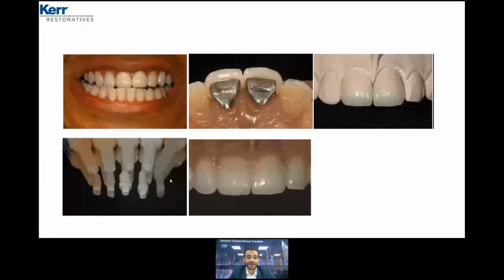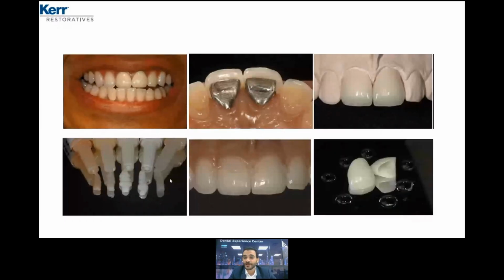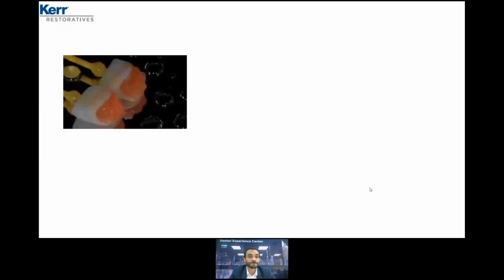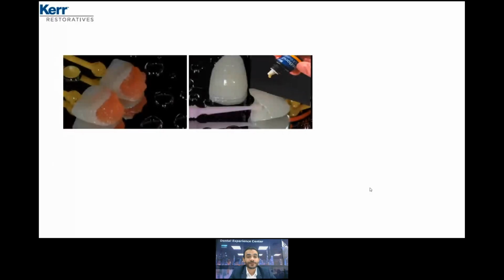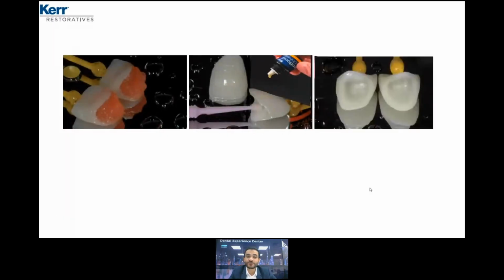Try first which shade you need to use by application of the try-in paste. Surface treatment protocol for the veneer or for the crown according to the substrate: feldspathic porcelain, zirconia, and Emax. Here, hydrofluoric acid for only 20 seconds. Application of OptiBond Universal.